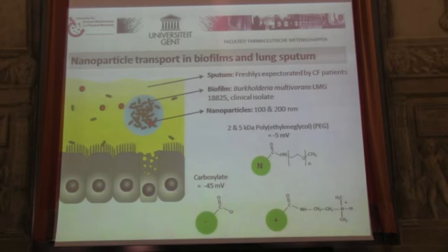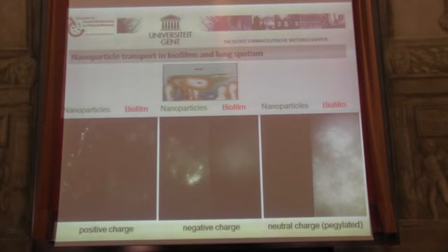Now the first thing that you have to wonder about is what kind of nanoparticles have this type of properties? How should we make a nanoparticle move through these very dense and sticky biolayers? And we studied this by model nanoparticles, polystyrene, fluorescent particles. We have them carboxylated, so a negative charge, aminylated with a positive charge, and pegylated to shield the charge. And these are in vitro biofilm experiments. I will start the movies. I hope you can see it. The contrast is not so great.